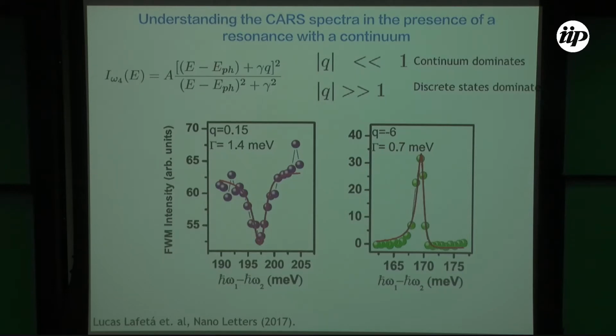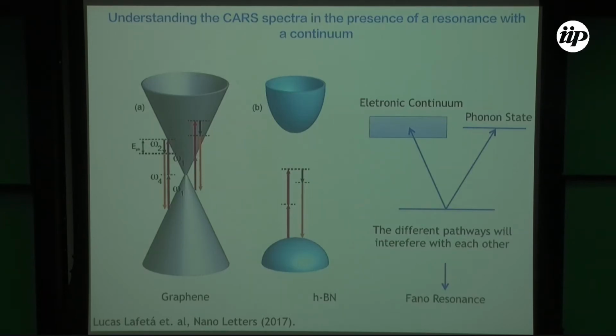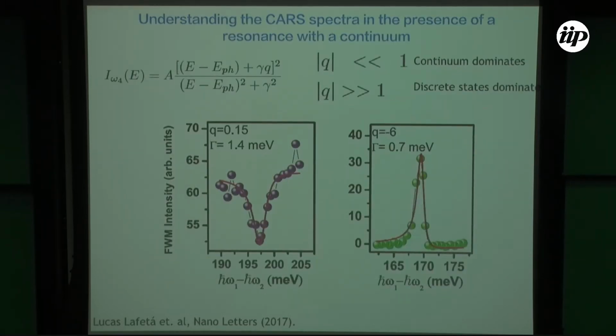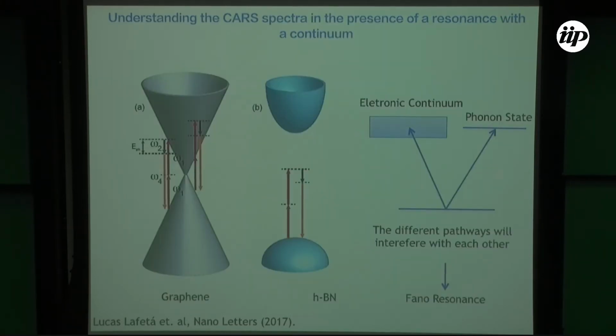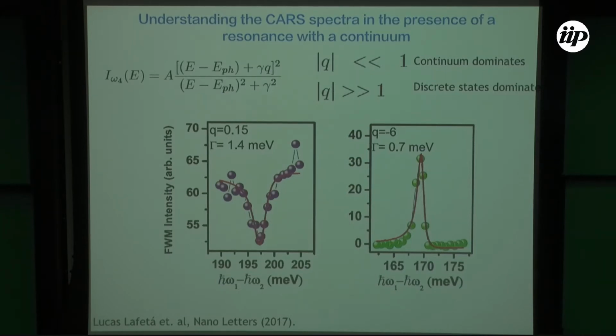So here's the phonon energy, okay? Gamma here is the phonon lifetime, okay? And also you have this Q parameter here. Basically, if Q is much smaller than 1, then this electronic continuum is going to be the strongest contribution. If this discrete state dominates the response, so this state is going to contribute more, okay? Then Q is much larger than 1.